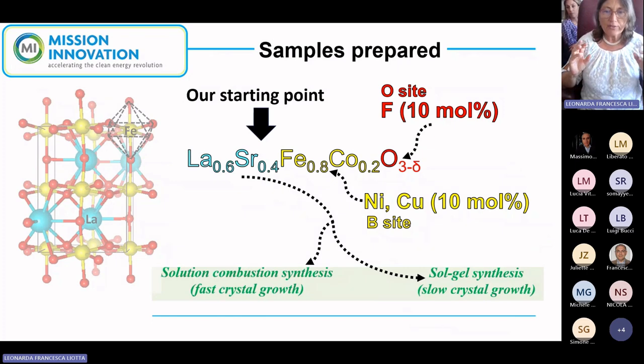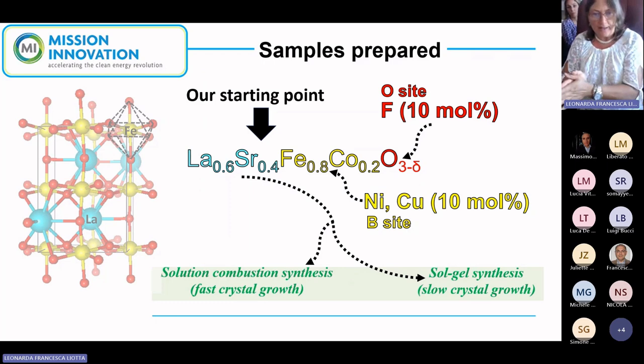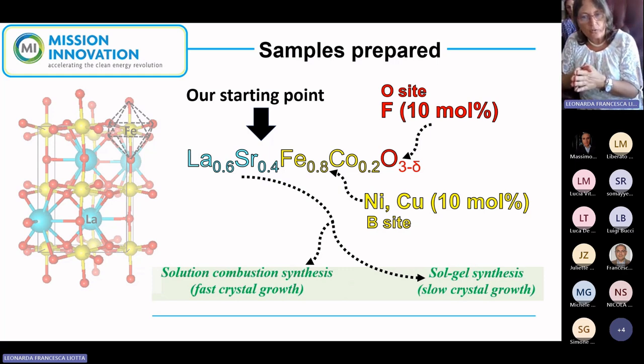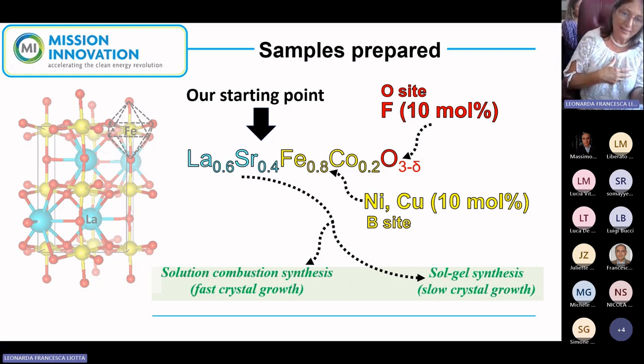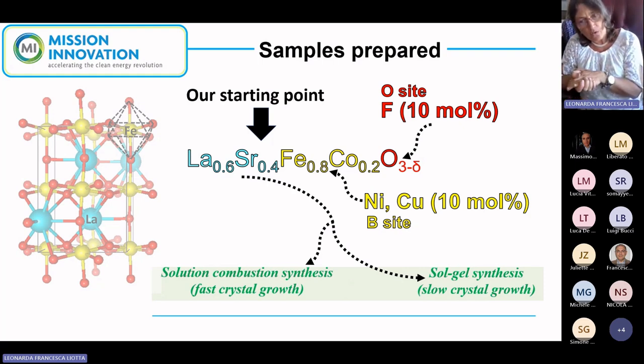Which are the samples that we have prepared, the type of samples. They are perovskite oxides, and we started from one basic structure, which is a lanthanum ferrite with 40% of strontium at the A site, which is fixed, and 20% of cobalt at the B site, which is also fixed. What is changing is the amount of iron, because we dope with 10% molar of nickel or 10% molar of copper that replace the iron site.